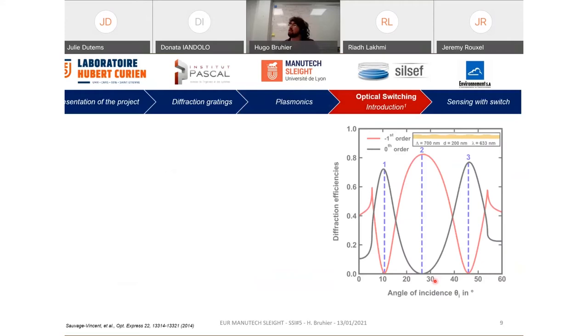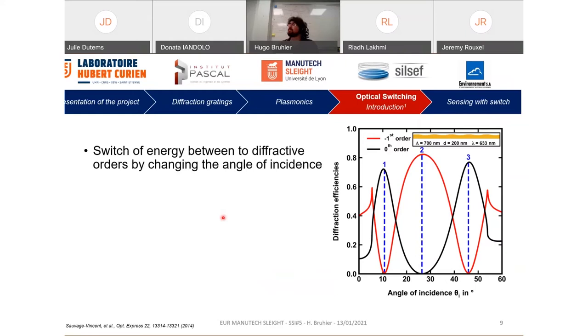Here is a typical curve of the optical switching effect. We call it optical switching effect because we have a switch of energy between two diffractive orders by changing the angle of incidence. At low angle, at 10 degrees, we have all the energy in the fundamental order. At 26 degrees, we have all the energy in the minus first order, and at 46 degrees, we also have all the energy coming back in the fundamental order.